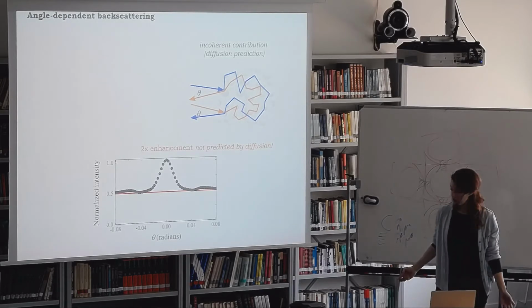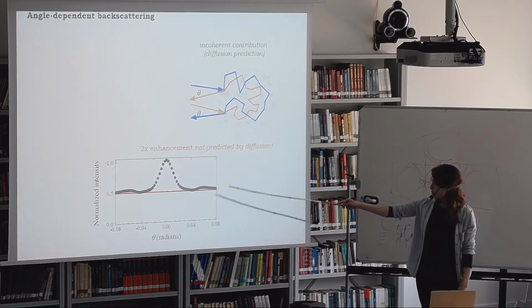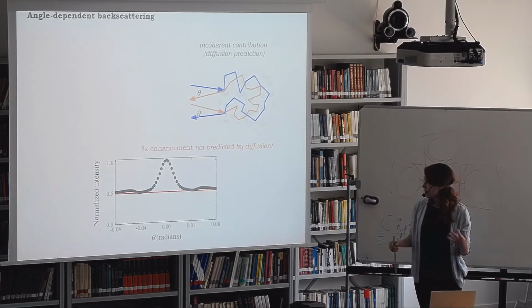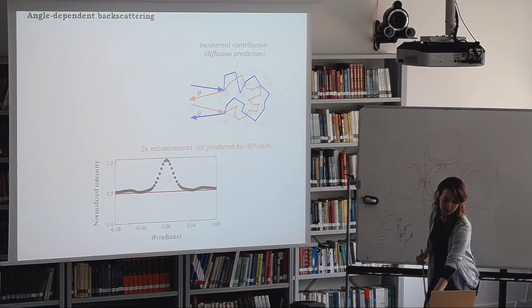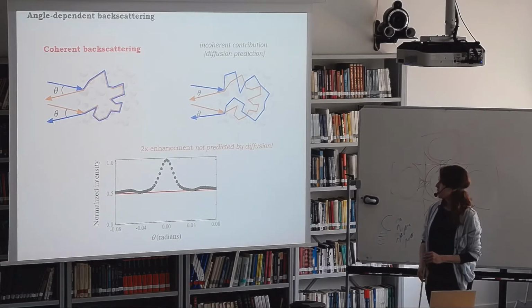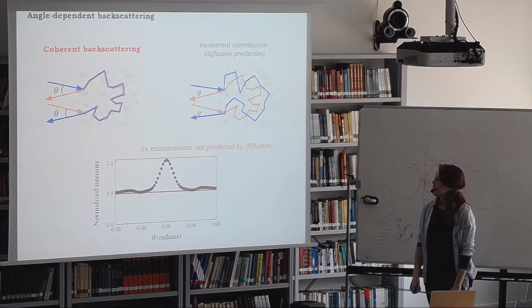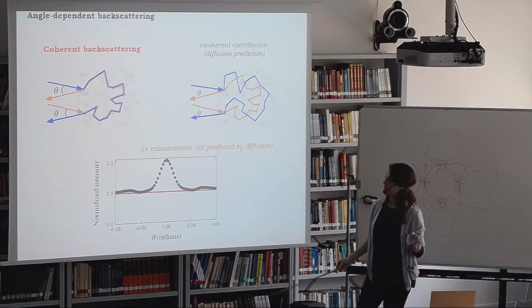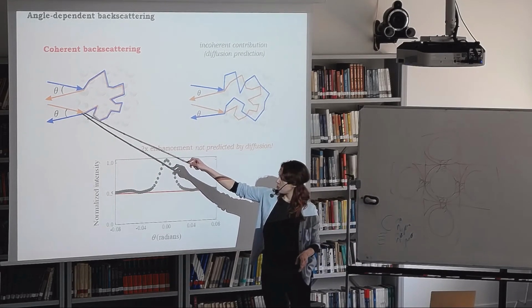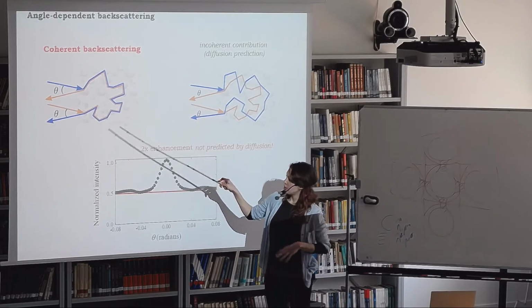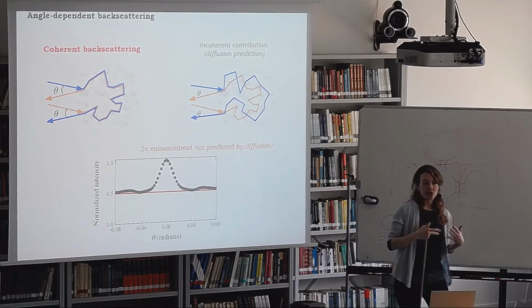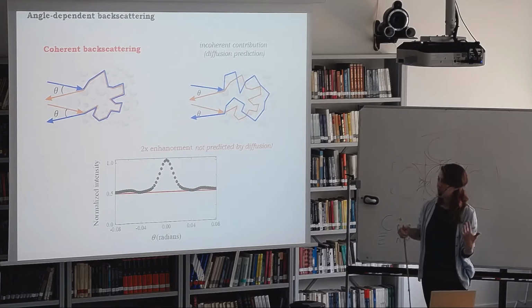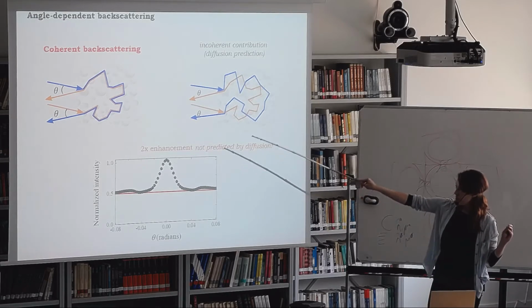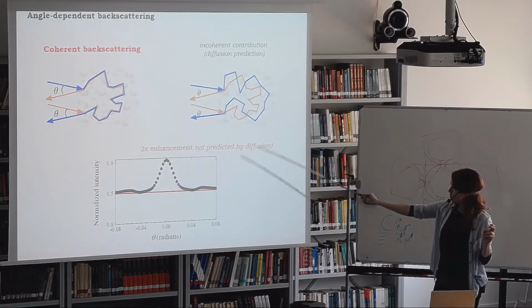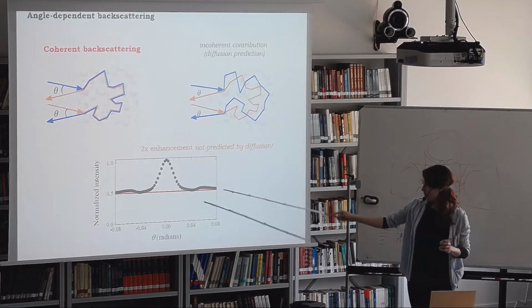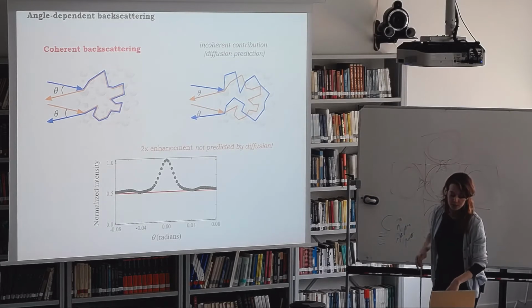However, if we actually do this measurement, we get something different. We get a sort of cone shape that's centered around 0 angle. And this is not predicted by the diffusion approximation. This is due to an interference effect called coherent backscattering. This occurs when you have waves that take reciprocal paths inside the sample. Essentially, these two waves are taking the same path, but in opposite directions. And so what happens is that they interfere constructively when you measure them outside of the sample. You get the highest constructive interference when the angle between source and receiver is 0. So you end up with, on average, this cone shape of intensity as a function of angle.